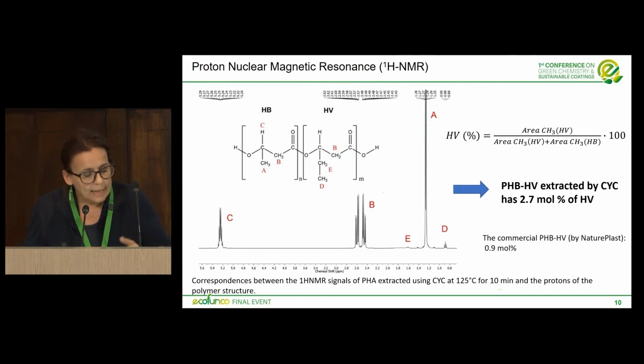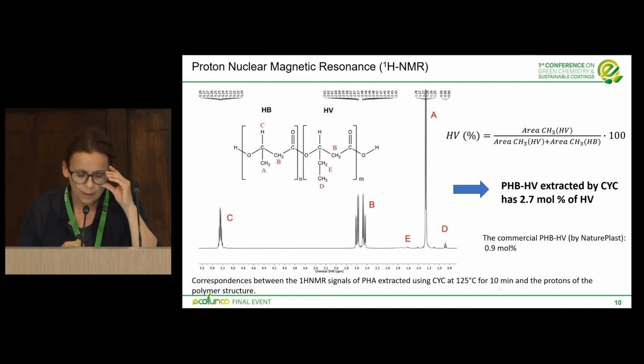So, the first analysis carried out was the proton nuclear magnetic resonance in order to evaluate the type of PHA extracted by cyclohexanone, and it resulted in PHB-HV containing about 3 mol percent of HV. And we have used in this work a commercial PHB-HV by Naturplast as a reference sample. In this case, this sample contains about 1 mol percent of HV. In this slide, you can see the equation used to evaluate also the amount of HV in the PHB-HV extracted by chloroform and also by cyclohexanone.